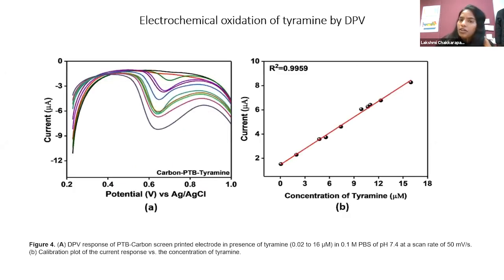We also use the differential pulse voltammetry technique in order to analyze the electrochemical oxidation of tyramine, because when compared to the cyclic voltammetric technique, the DPV method is highly sensitive, and here you could analyze really much lower concentrations, like nanomolar concentration of analyte. So in this result, we have analyzed the 0.02 micromolar to 16 micromolar range of tyramine in the presence of phosphate buffer solution, pH 7.4 and scan rate 50 millivolt per second. So the first addition should be 0.02 micromolar, and then it started increasing after each addition. The calibration plot represents the DPV response of the oxidation peak at 0.65 volt, the current response against the concentration of tyramine.